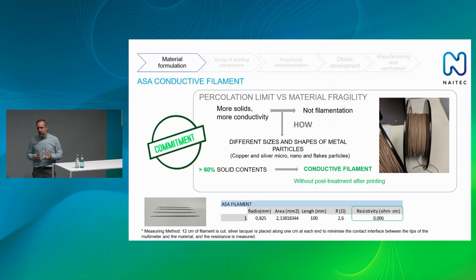In this process, there are two properties that are one against the other. For the conductivity, we would like to add as many metal particles as we could. And actually, if it was directly metal, it would be ideal. But then it would be rigid and it couldn't be printed. So we need to find the compromise, the balance between the number of particles and the amount of polymer that's still in the filament. After a huge number of experiments and some optimization processes, they have found a combination of copper and silver nanoparticles, microparticles, and also flakes, that is over 60% of the mixture with the polymer, to still be able to filament this material, and that has the best conductive properties from all the tests.